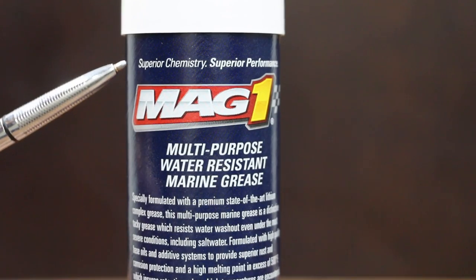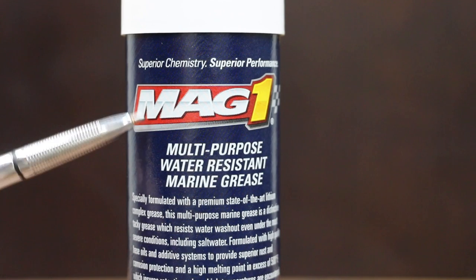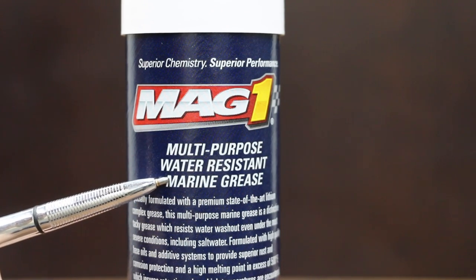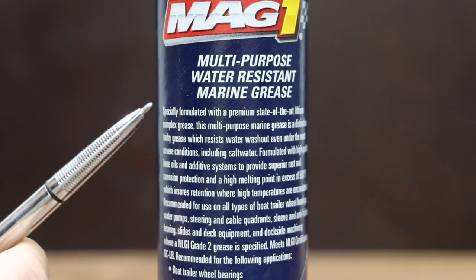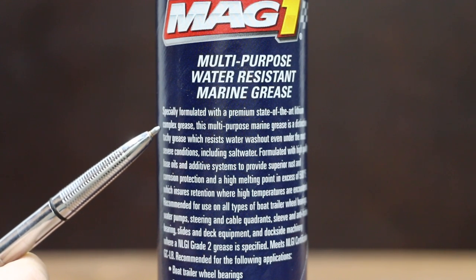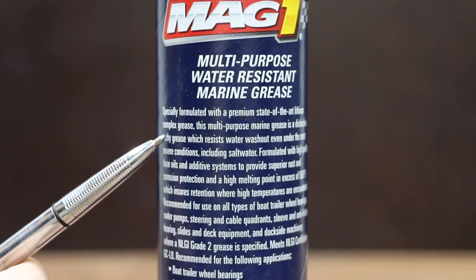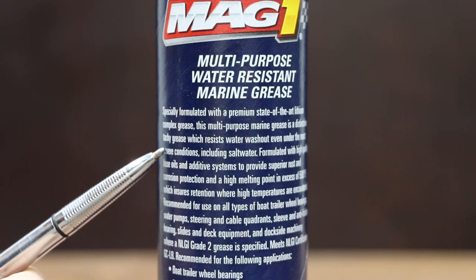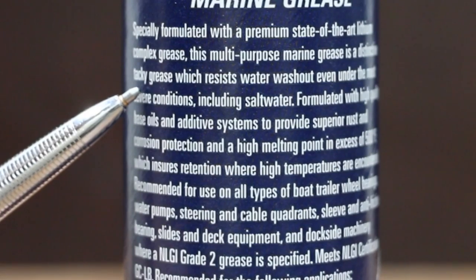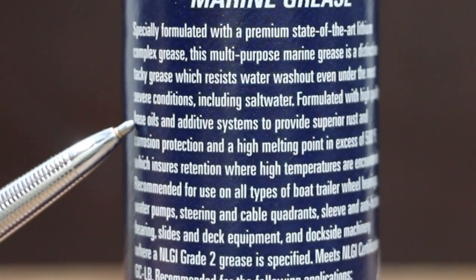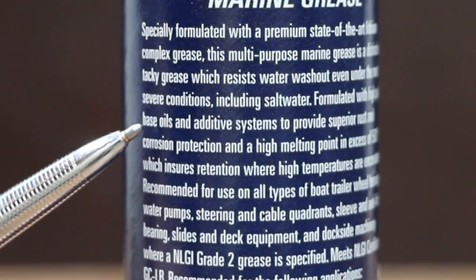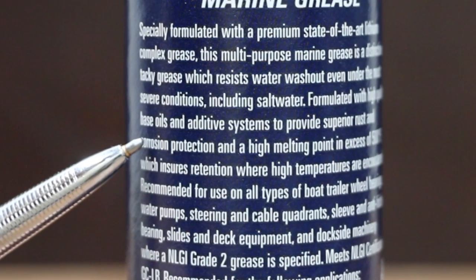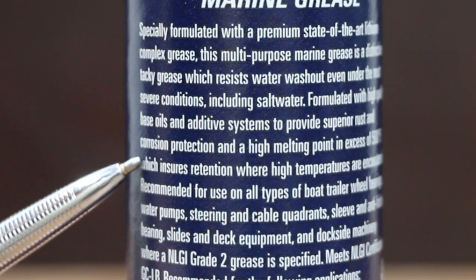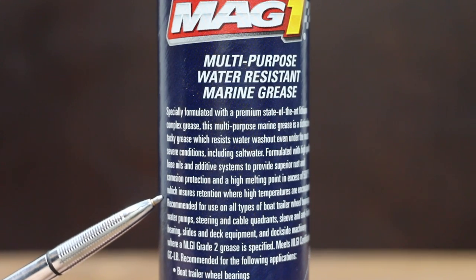The Mag 1 grease claims superior chemistry and superior performance. Multi-purpose marine grease that's water resistant. Specially formulated with a premium state-of-the-art lithium grease, this multi-purpose marine grease is a distinctive tacky grease which resists water washout even under the most severe conditions, including salt water, formulated with high quality base oils and additive systems to provide superior rust and corrosion protection and a high melting point in excess of 500 degrees Fahrenheit, which ensures retention where high temperatures are encountered.